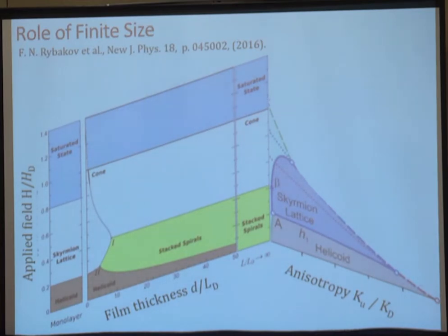You mentioned something about the fitting which I wasn't sure I understood. The parameters had to be assumed, so you have basically an input that's alpha and then there's also one line. Right, that's right. But then, are there too many parameters? If we start off with four fitting parameters that have no field dependence, then you can't fit the data, no matter which choice of parameters. So what we do is add a fifth parameter, that is constant over the cone phase and zero above, in the perpendicular phase. Another way of saying it is that alpha is different in the cone phase and in the perpendicular phase. So a different set of parameters. The cone phase is really just the same, and then maybe the opening angle of the cone, you don't expect this parameter to be constant.